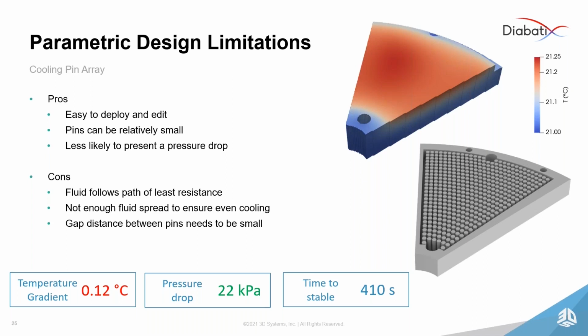And if we evaluate how this behaves, I summarized 3 key parameters there. First of all, you see the thermal gradient, which was 0.12 degrees Celsius for this design, which was way too high. A pressure drop of 22 kilopascal, which was very good, because the limit was 70 kilopascal, but still it's not solving the issue of a minimal thermal gradient that you want to have in these cases. And the time to a stable temperature was 410 seconds.